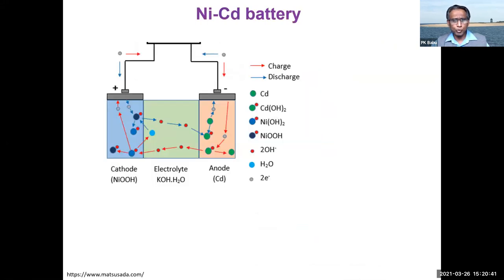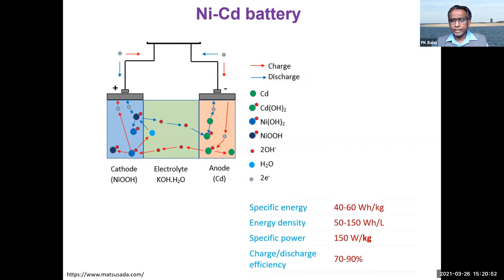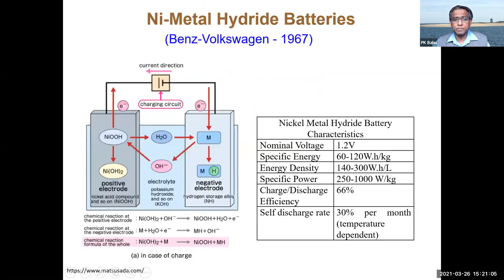A huge improvement can be seen with the next nickel battery, which is the nickel cadmium battery. The anode in this case is cadmium. It has specific energy of 40 to 60 watt hour per kilogram. The energy density is quite high, 50 to 150 watt hour per liter. Charge discharge efficiency, nearly 90%.